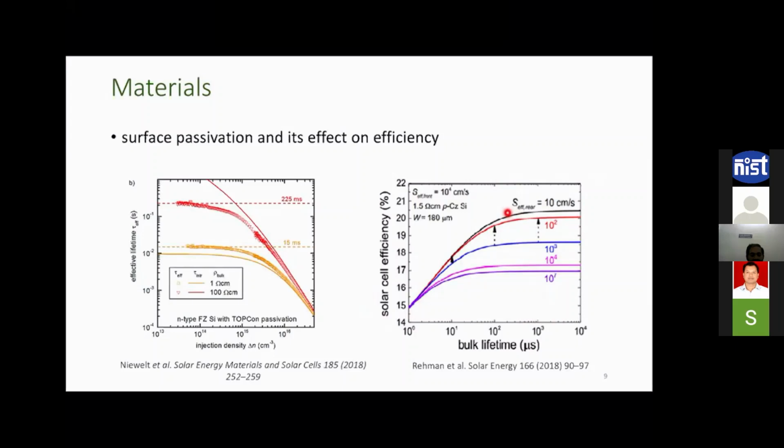That means the surface recombination or the lifetime associated with the surface recombination is less. So you can see the recombination velocity increases downwards. Here you are having minimum recombination velocity, which is 10 centimeter per second. And here you are having maximum surface recombination velocity, which is 10 to the power 7 centimeter per second.